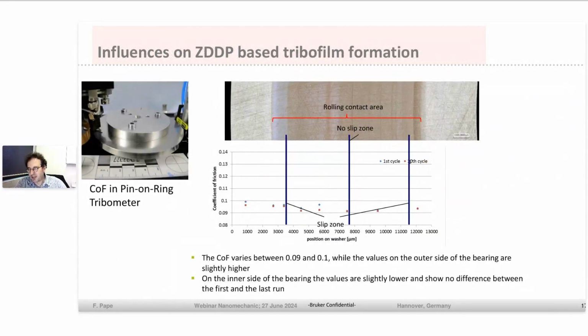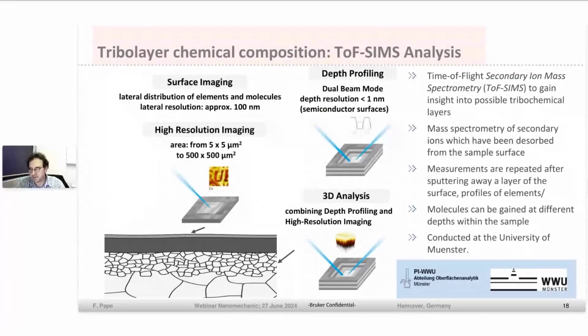We also did some measurements with a pin on ring test rig shown on the left, where we can see that the friction of this tribofilm is quite low with a value of 0.09 to 0.1, while outside it's slightly higher. So we can also achieve the frictional properties of this tribofilm, but with the pin on ring tribometer, not as precise as we would like to do.